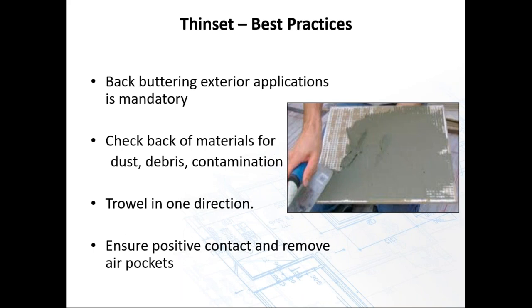When we get into exterior applications, the practices of how to install the mortars, making sure that we're getting the right coverages. Backbuttering for exterior applications is mandatory. On an exterior application, we're trying to achieve a 95% coverage of the mortar to the substrate. So if you take down a tile and you're seeing ridge marks, you're not getting that 95% coverage. What we're trying to do by getting this coverage, as you're seeing in this picture, is the installer takes the mortar, flat side of his trowel, and combs it across the back of the tile, achieving full coverage onto the back of the tile. He'll then comb the wall, placing the tile onto the substrate, trying to achieve this 95% coverage. We'd like 100%, but there's always a void somewhere. But 95% is what we're going for, and that's industry standard for an exterior application.